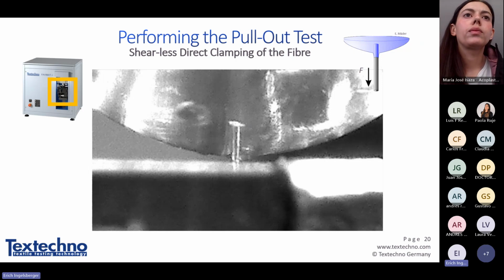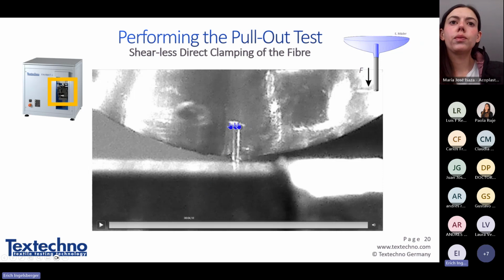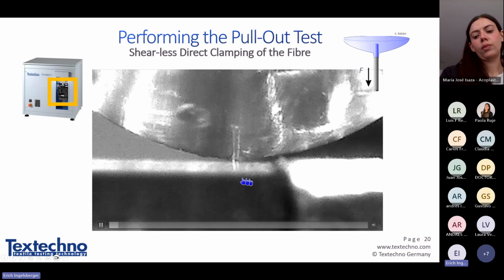So there are two or three important points. The first is the point where the crack initiates. This is the force or stress where your composite starts to fail. Then we measure the maximum force, and this will drop. The force will drop at that moment where the fiber is completely dissolved, not only after the first crack.